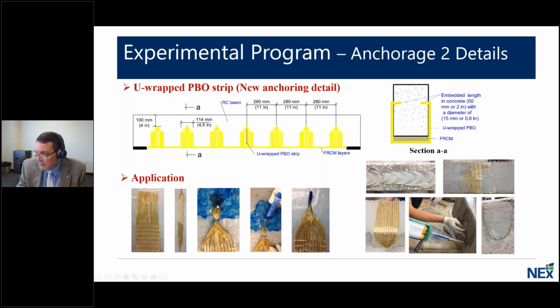So again, similarly, we impregnate it. In this case, we're using an epoxy. And again, this wraps around the system, again, to help try to prevent a premature debonding type failure.